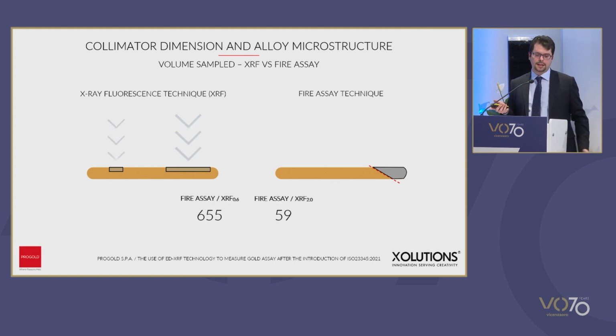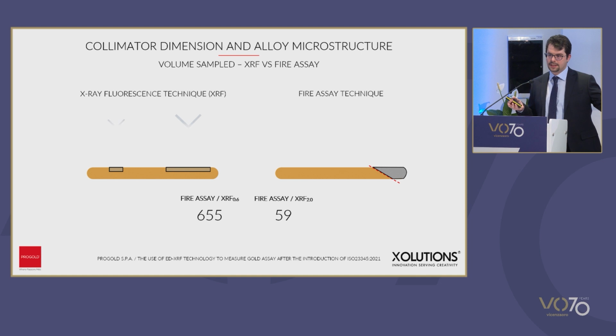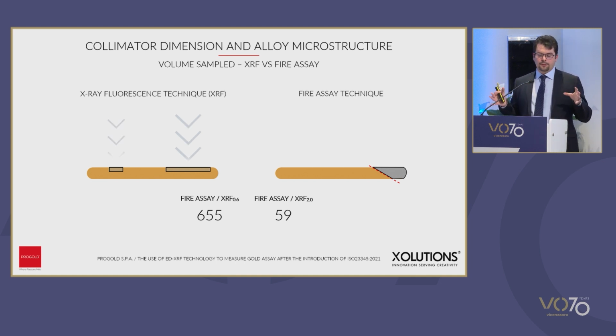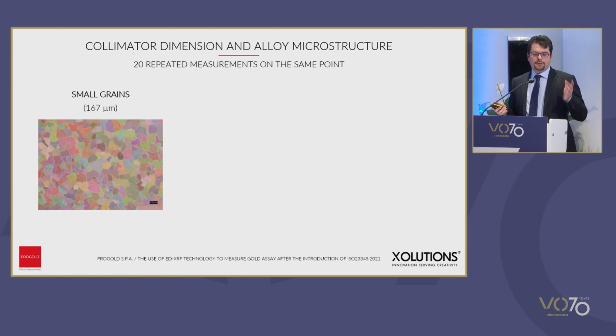Now, if we use the Lambert-Beer equation, what we achieve is this. And if we use a smaller collimator, which is on the left, the fire assay will involve 655 times more atoms than the XRF analysis. But if we increase the size of the collimator, this ratio will go down dramatically, down to 59 times. And this suggests that the bigger the collimator, the more the quantity of atoms is similar to the technique used for fire assay.